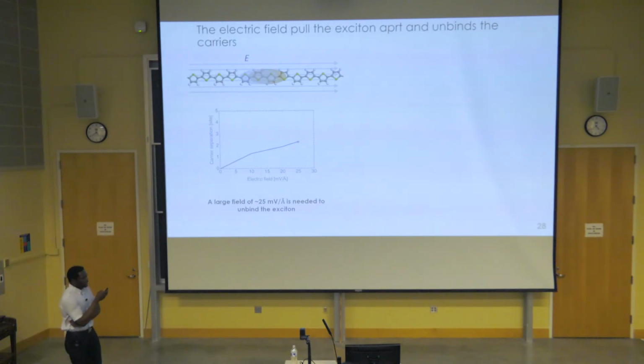So next we look at what happens when we apply an electric field on this exciton. We observe that the electric field increases the separation distance between the two charge carriers, as shown in this figure. We have an increased distance between the hole and the electron as we increase the strength of the electric field until we reach a value where the exciton is completely unbound. And the field strength for the system we are particularly looking at is rather large, at 25 millivolt per angstrom.